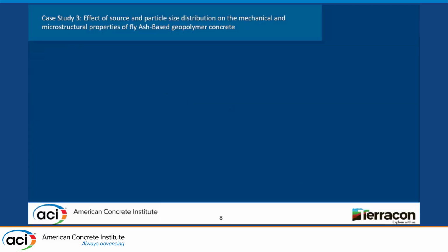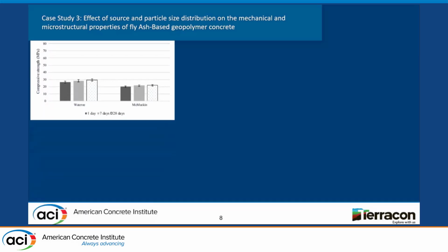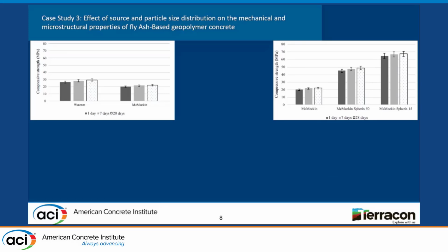So then I wanted to see the effect of the fly ash source. As you can see in the first case study, the fly ash source can really affect the compressive strength. So I wanted to see how about if I change it again to another one. So I will compare the Wateree versus McMaken fly ash source. And you can see also there is a slight effect on the compressive strength due to changing the fly ash source. And also I wanted to see the effect of the particle size distribution for the same fly ash.